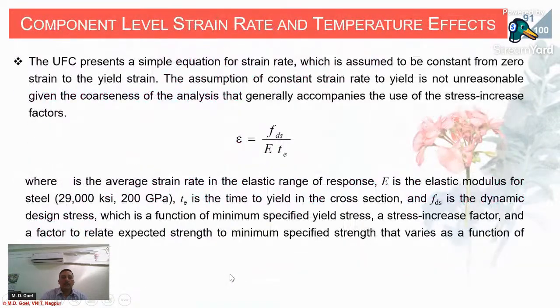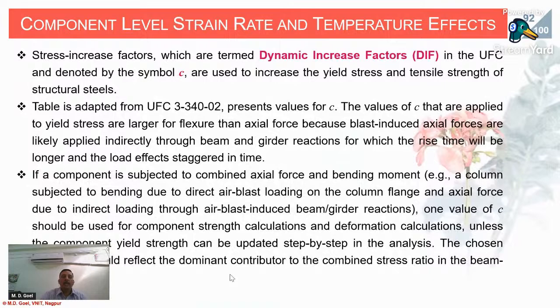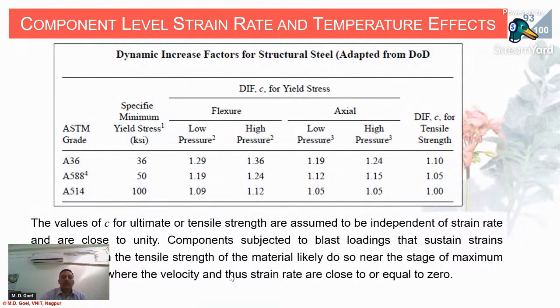So this kind of work can be carried out, and if you don't have anything, you just adopt the dynamic increase factor. For example, the Department of Defense is giving these for different US steels. For Indian steel, it is still not available because nobody has worked on it. But for other steels, ASTM grade steel A36, A588, A514, depending upon their minimum yield strength in KSI, kilo pounds per square inch, it is given that if it is in flexure, low pressure region, high pressure region, then use these factors.